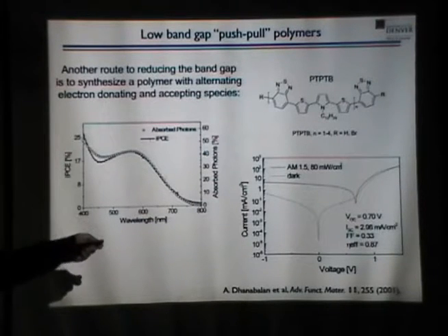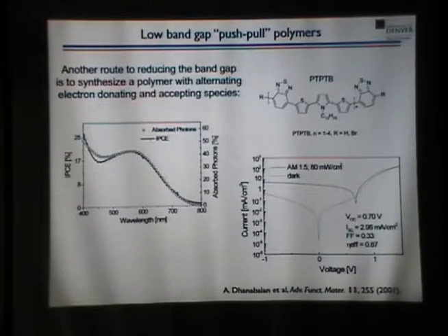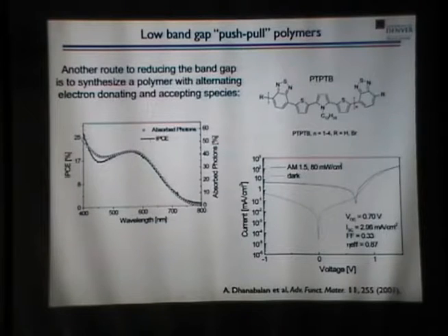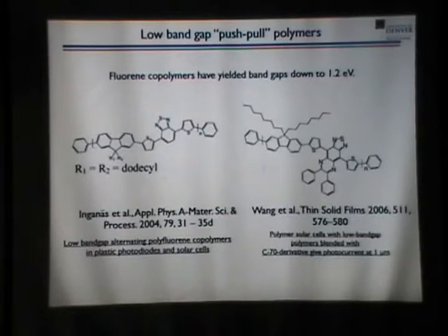And this is one of the prime design motifs we have now for all of our materials. So this guy had a band gap of about 1.7. And they were able to make some okay devices, got efficiencies. This was a 0.87% efficient device, or close to a 1% device. So it was not a great world record, but it showed that this design principle worked. So people use that now to move on to much more sophisticated materials. I'll just show a couple quickly.